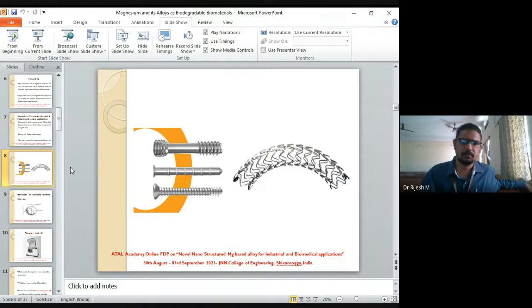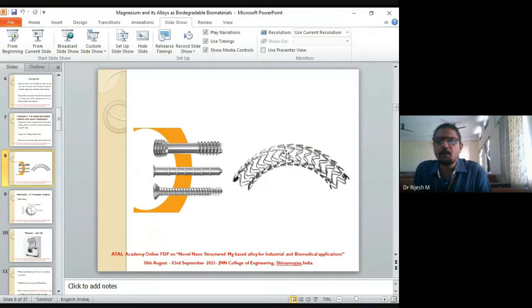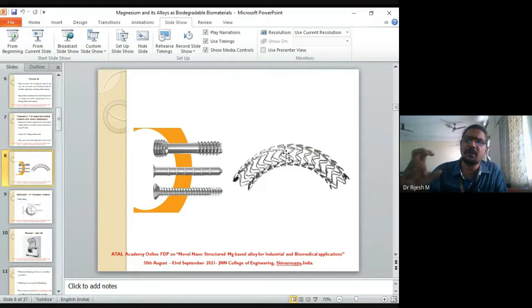See, this is what it is. You can see the screws made of magnesium, and this is a stent. If you have a block in the heart, they insert the stent. Stents are small in size, and they are inflated. Stents were made of polymers before. When you use polymers for stents, the structural strength is not that good. Whereas when you go for magnesium, the strength of the stent is very good. They become very stiff, and the stent remains for a longer time. You don't take the stent out.